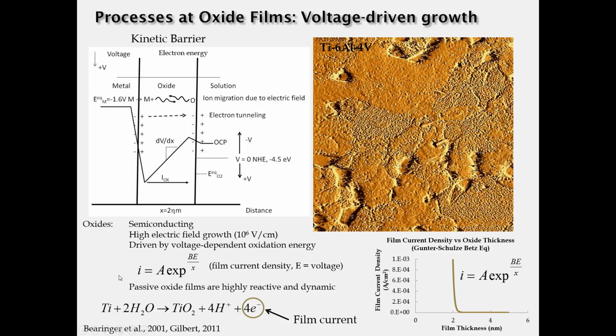We've known since about the 1930s that the currents associated with reforming oxides, repassivating oxides, vary according to this equation, which was developed by Gunter Schulze and Betz. It shows that the current varies with the thickness of the oxide in this e to the 1 over x behavior. I plot that function over here on the bottom right to show you how steeply falling the current is as the film gets thicker. In fact, it essentially falls to 0 very rapidly at a limiting thickness of the oxide film.